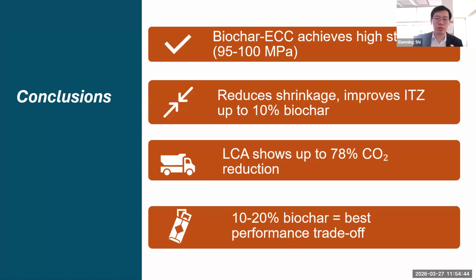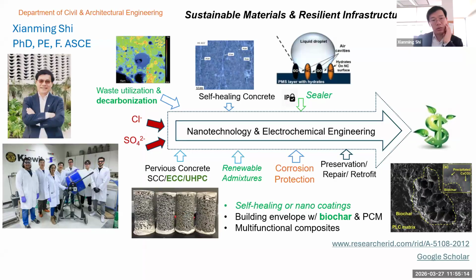So to conclude, biochar ECC can achieve high strength, 95 to 100 megapascal. And we can improve the interfacial transition zone up to 10% replacement of cement. And the environmental life cycle assessment shows up to 78% CO2 equivalent reduction. And the overall balance is that if you only replace 10 to 20% with biochar, you probably achieve a good trade-off. So with that, I conclude my talk.